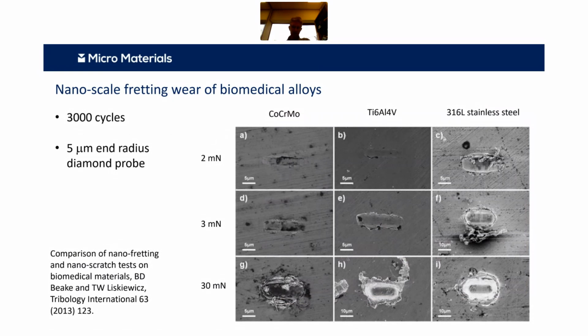It has the highest H³/E², so it has the highest load carrying capacity of these different materials at these small scales. But then as you go on, once you're breaking that structure, you have this quite severe damage that you can see in that H there, and you're getting this sort of delamination type wear, which is detrimental. That sort of thing is typically a problem with titanium alloys in these biological applications. They're quite sticky, which doesn't help.